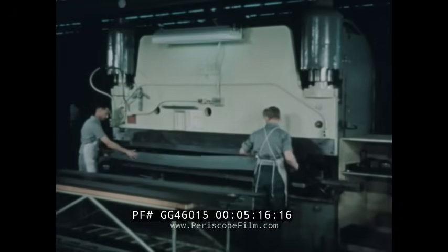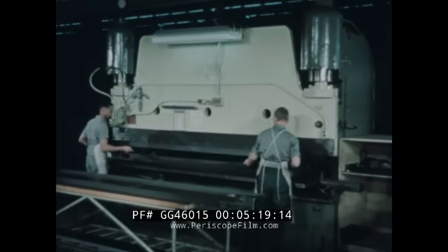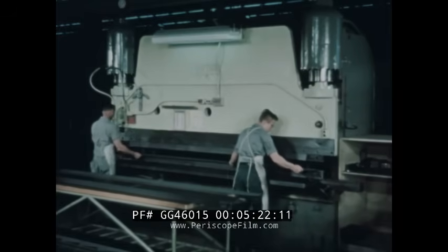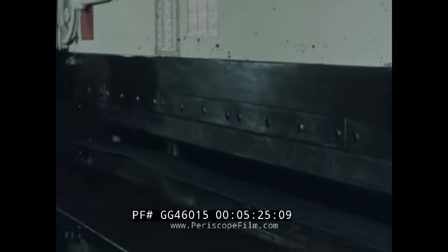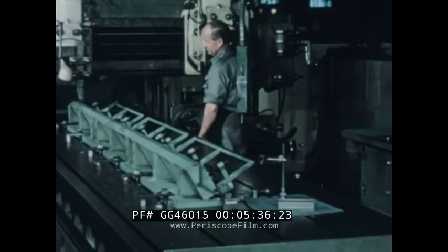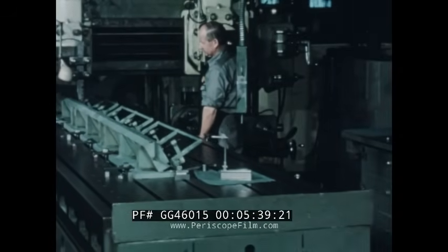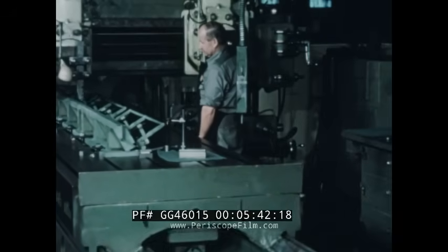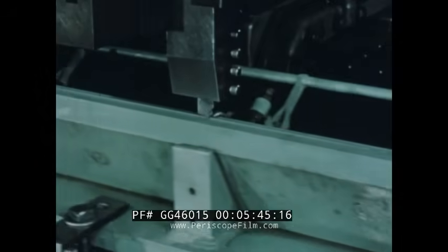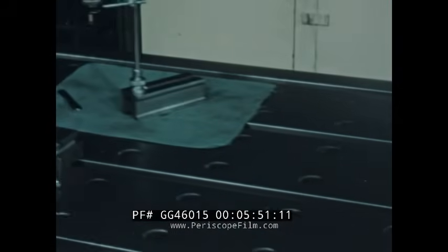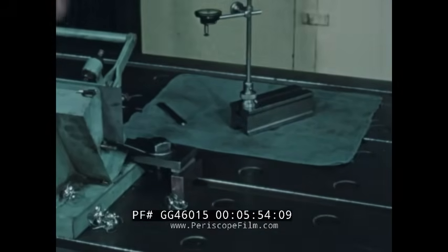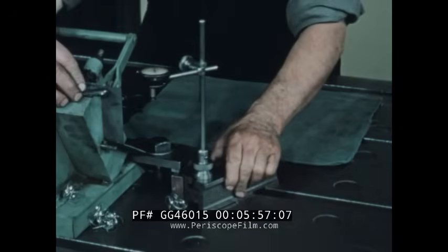The zirconium cans, which enclosed the graphite moderator blocks, were fabricated from six separate longitudinal panels. The formation of each panel was completed in a single brake operation. This is a 60-degree bend. The formed panels were machined to the specified width. This operation was critical, since it determined the tolerance on the completed moderator can. Tolerance across the flats was 1/25,000th of an inch.